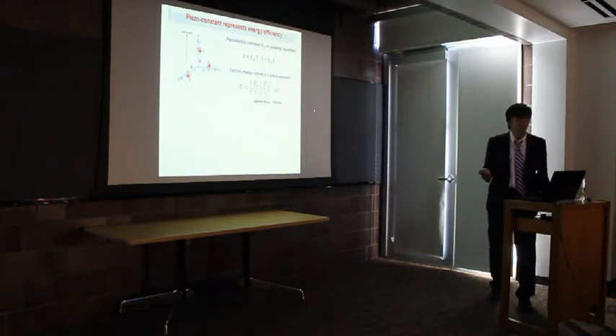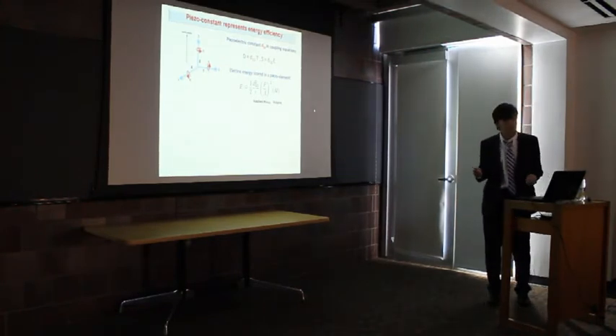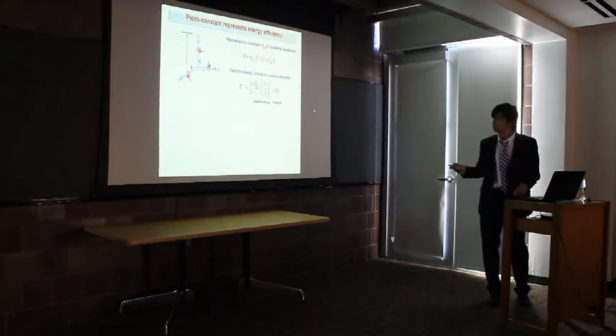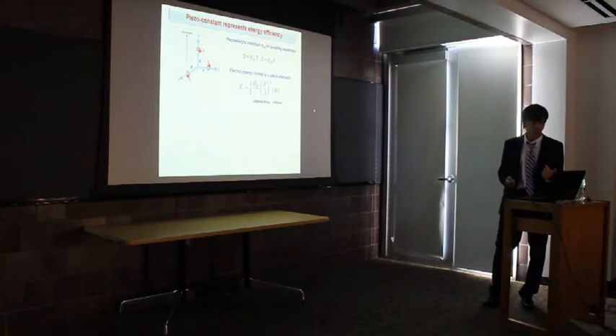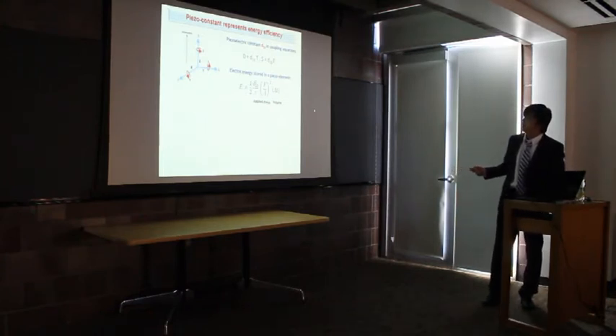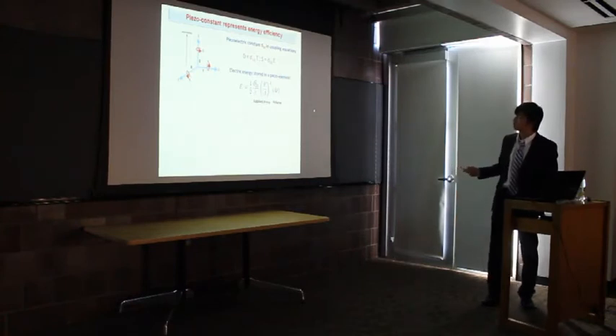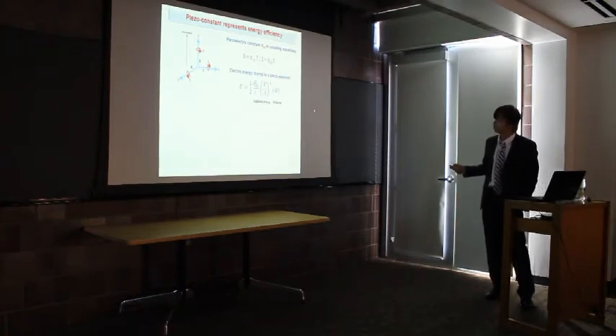Looking at the theory of piezoelectricity, the most important parameter to keep in mind is D33. This is the piezoelectric constant. The number 3 just stands for the Z direction, as we simplify the system by looking at one direction of polarization and deformation. So D33 appears in the coupling equations. They tell you how much polarization the material has under the applied stress T, and how much strain the material can deform under the applied electrical field E.